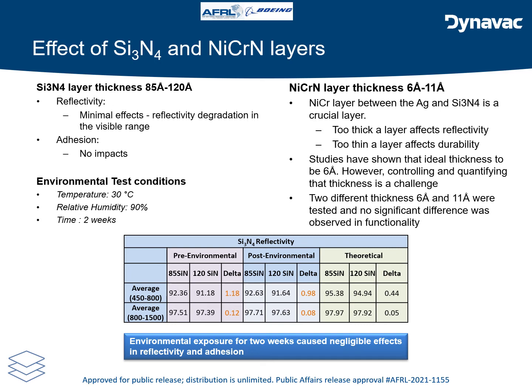Effect of silicon nitride and nickel chrome nitride layers. As we discussed earlier, the thickness of these layers is very critical in obtaining the desired results on the optical and durability factors. Silicon nitride layer thickness, we varied it from 85 angstroms to 120 angstroms, and we looked at the reflectivity results, adhesion results, and also did some environmental testing, basically putting these samples through a high stress test. The conditions were 30 degrees C at a relative humidity of 90% for 2 weeks. Within this thickness regime, we did not see any adverse effects with silicon nitride thickness.